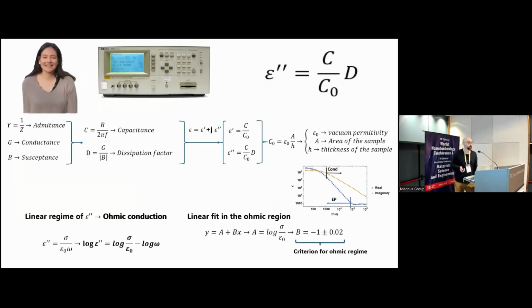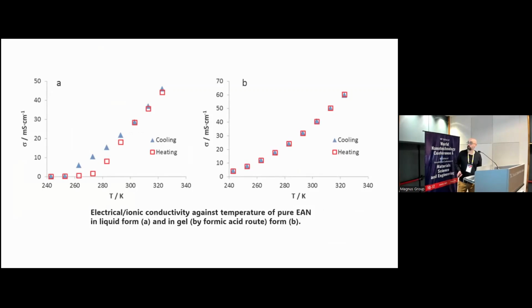These measurements were primarily done by my colleague Antía Santiago. And relating capacitance, dissipation factor, the vacuum permittivity, the area of the sample with the thickness of the sample, we can get the ohmic conduction of our compound, and we can get the electrical conductivity of the sample. You can see here the results.